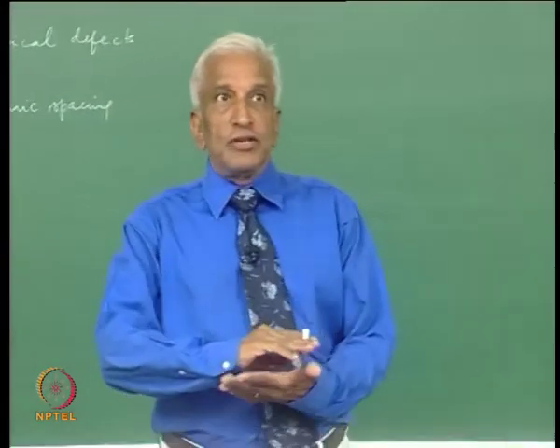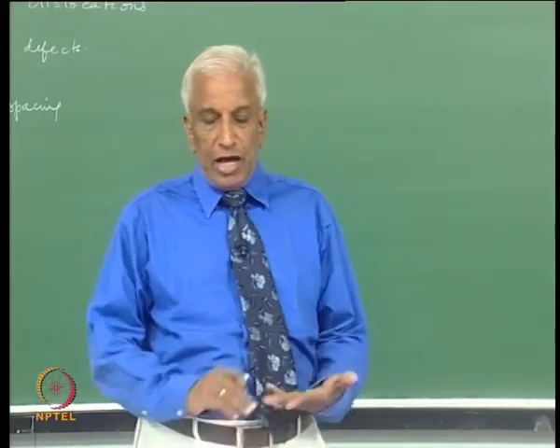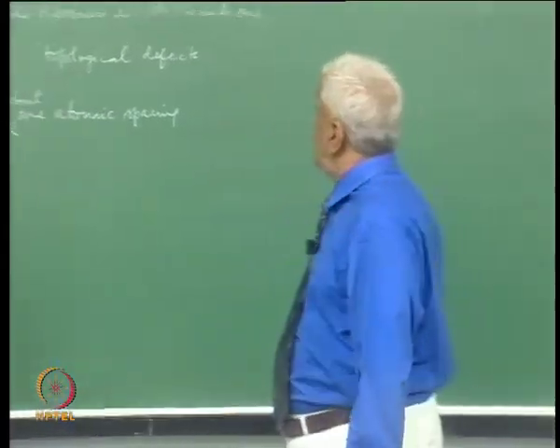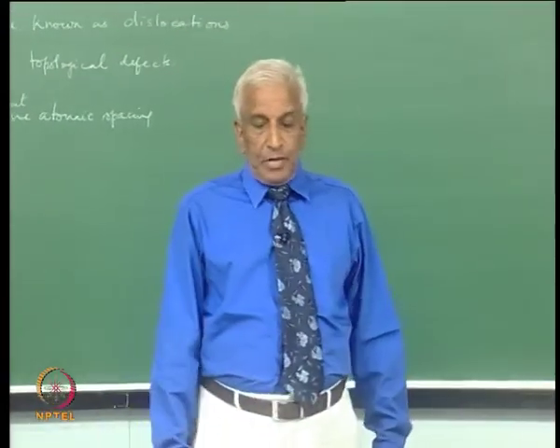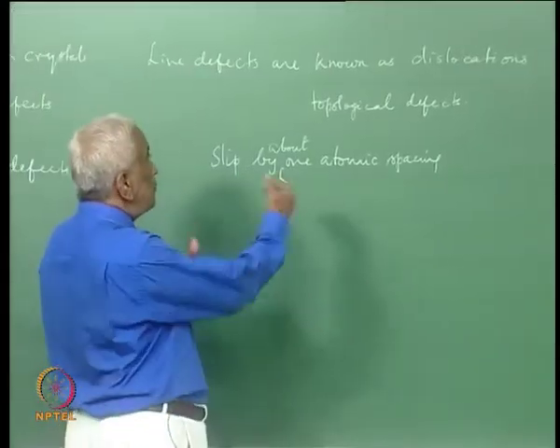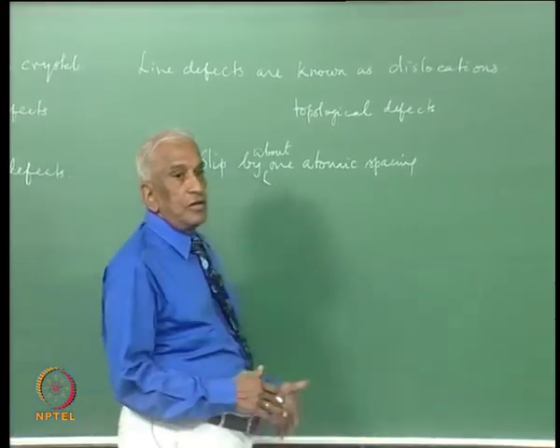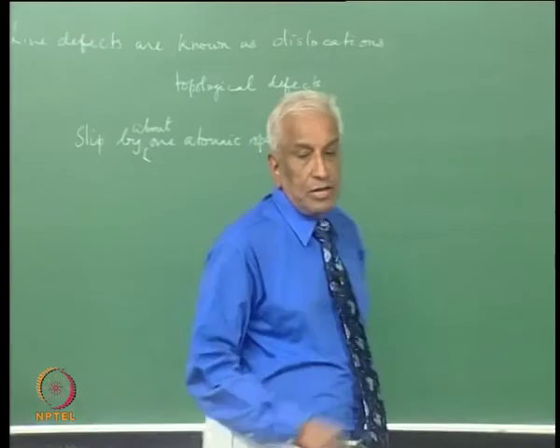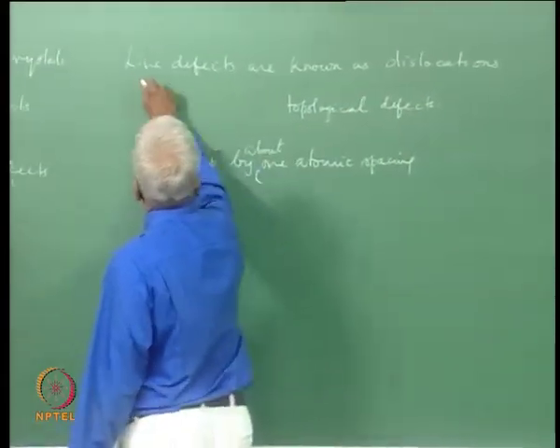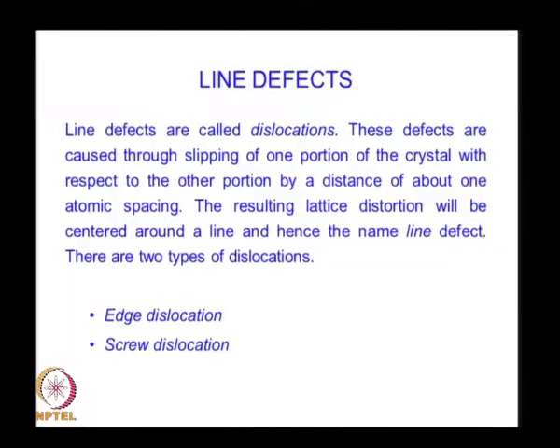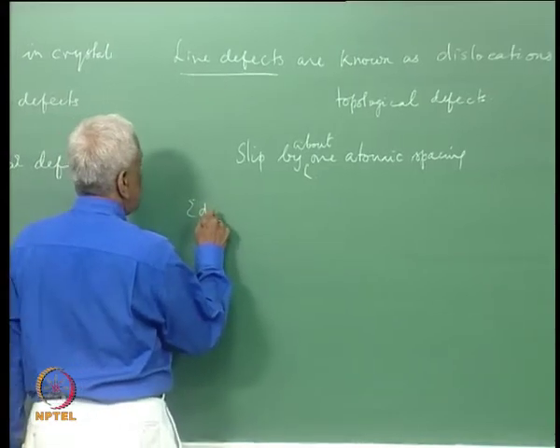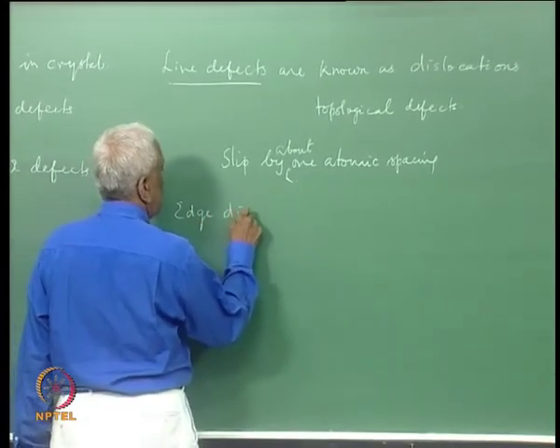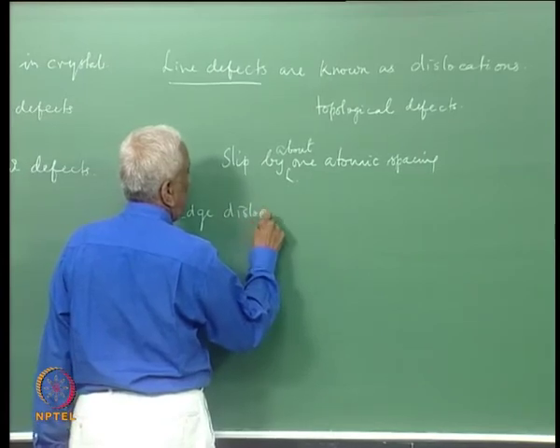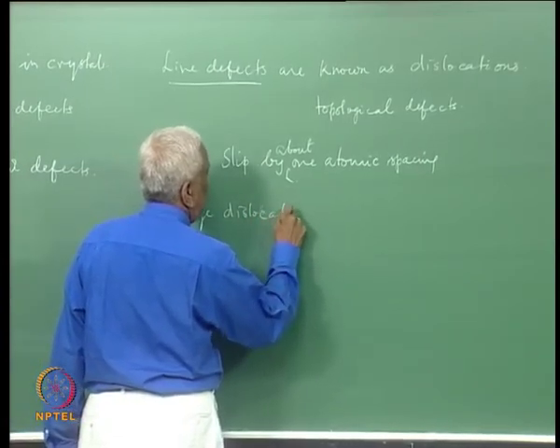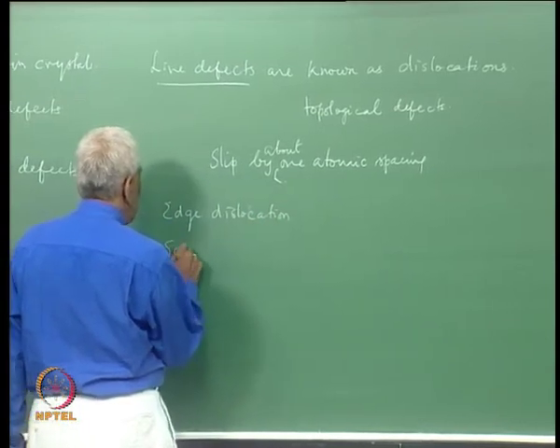So, one portion of the crystal slips with respect to the other by a distance of the order of one atomic spacing. Therefore, the lattice will be distorted and this distortion will be centered around a line, and that is the reason why we call it a line defect. We can have two types of dislocations. One is edge dislocation, while the other is called screw dislocation.